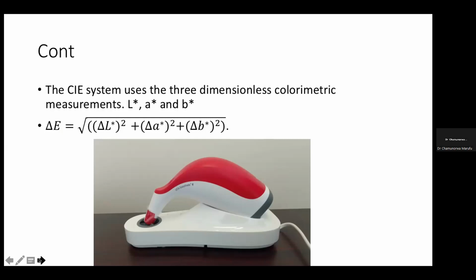In this study, we use the CIELAB color system, and we use the spectrophotometer to measure the color changes. So when you measure the color using this system, the color is measured at 3 coordinates, which are designated L star, a star, and b star. And then to get the color difference between 2 points, you simply subtract the initial from the final color coordinates, square them, and then you find the square root of that, and that will be designated delta E, as in delta E is the color change.